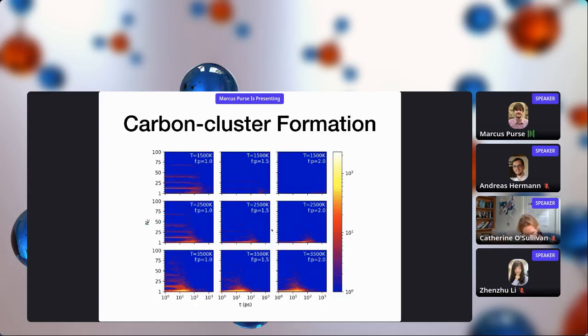So I think one interesting thing that's very apparent here is that with low formaldehyde to phenol ratios, methylene bridge breaking is very obvious. You can see that you form regular sized fragments, which equate to repeat units from the polymer. And this is much less apparent at higher temperatures.